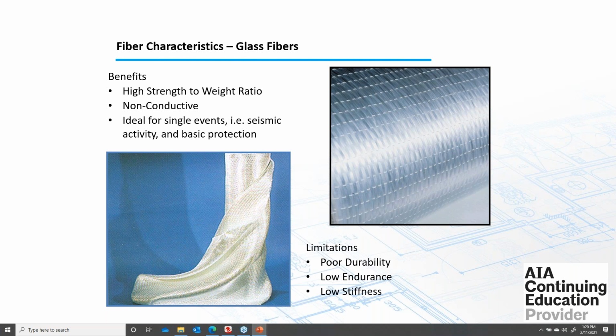The exception to that kind of rule would be for masonry, which we're really not talking much about today. But because masonry is much lower strength than the carbon, sometimes carbon is actually too much stiffness for a masonry wall. So you would use the glass in that situation, just because it provides a closer amount of capacity to what's already there. You just have to apply more severe durability reduction factors to it, which both the CSA S806 code and the ACI 440 code address when you're designing.